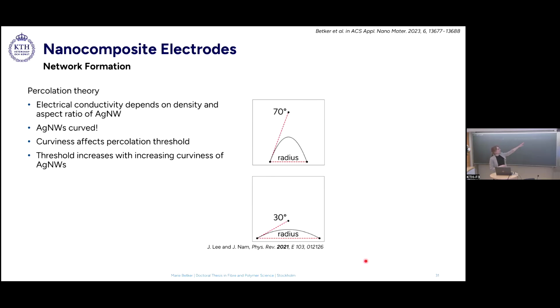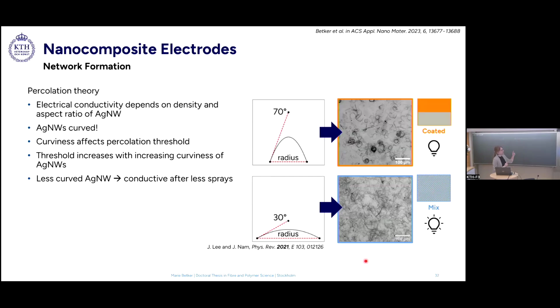And you can see here they compared a highly curved nanowire, which has a small effective radius, and a less curved nanowire, which has a large effective radius. And what they found is that the percolation threshold actually increases with increasing curviness. And this is exactly, again, what we see for our electrodes. So again, the same two types. In orange, the coated one, we see that the nanowires are highly curved, while in the mixed one, they are less curved. And this is the reason why this mixed type actually becomes more conductive after fewer spray pulses.